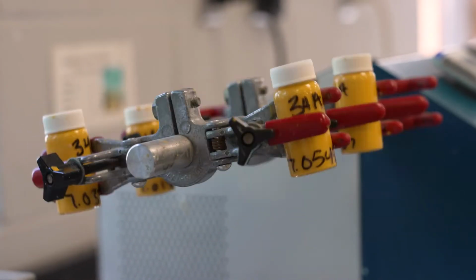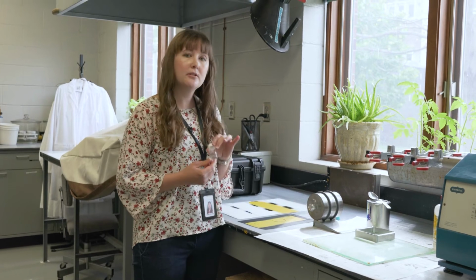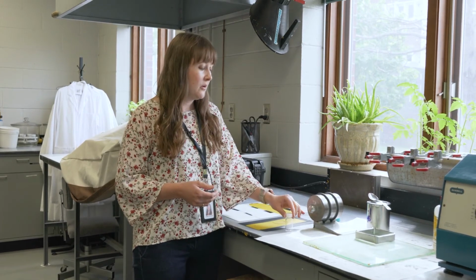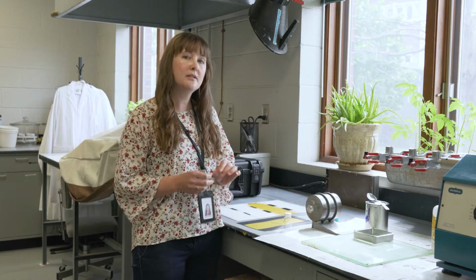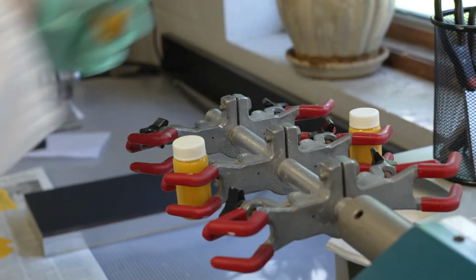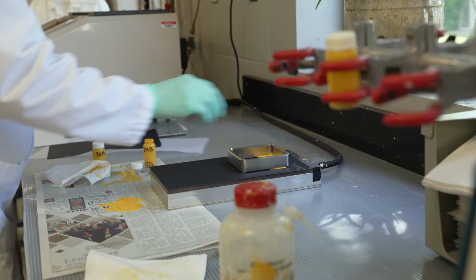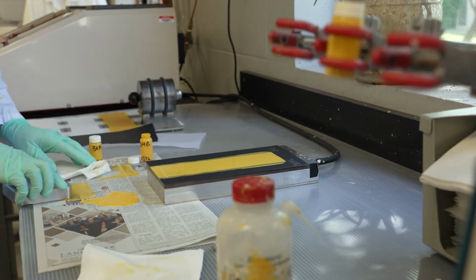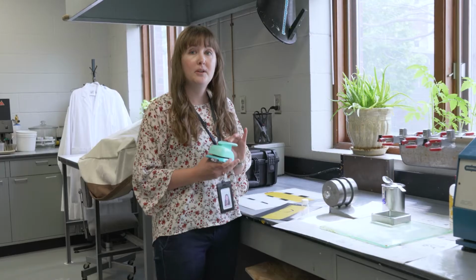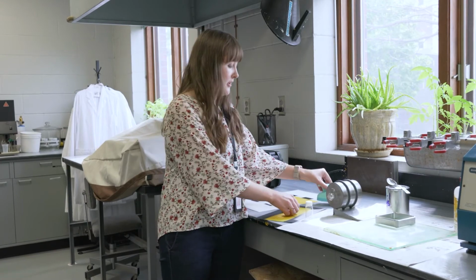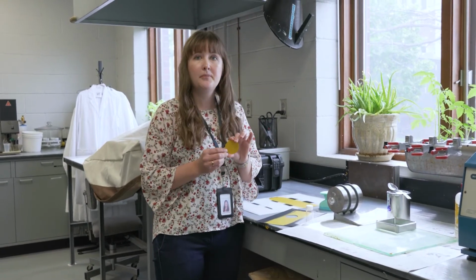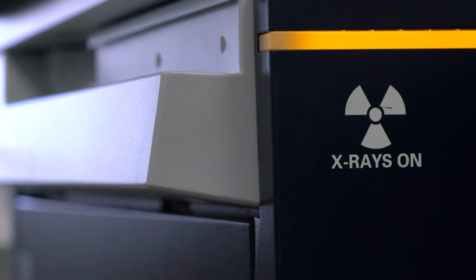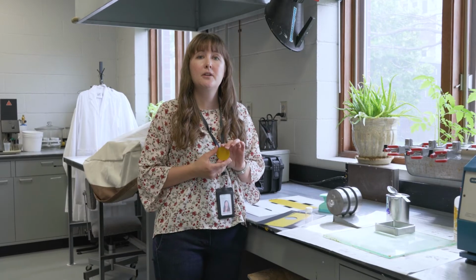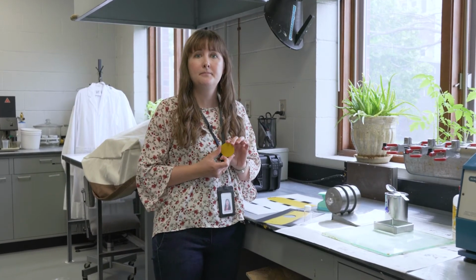We test titanium dioxide in the traffic paint. This is the active ingredient that causes reflection, and we measure out a certain amount of paint in a bottle. We add an additional chemical to it, and we shake it up. We have a wrist action shaker, and we do a drawdown, again at a really thin thickness. We use a giant hole punch to punch out a perfect circle, and we put that in our X-ray fluorescence spectrometer, and it determines our titanium dioxide content.